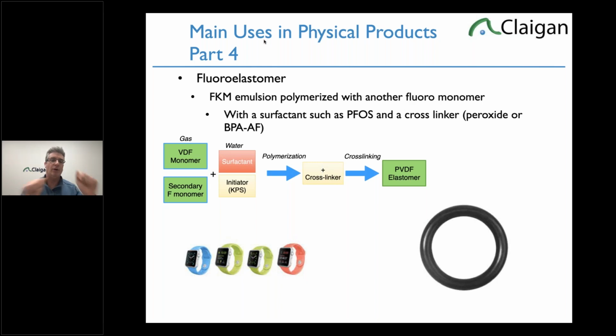That creates a plastic. We're not trying to create a PVDF or Kynar plastic. So Kynar is a solid PVDF. It's the tubing you see for a lot of water or chemical. It's rigid. If you want the rubber version, you have to vulcanize it. You have to cross-link the different polymers. They have to cross-link so it becomes a jumbo cross-linked network instead of rigid, and it becomes a rubber. So you have to add a cross-linker, which is peroxide or bisphenol AF.